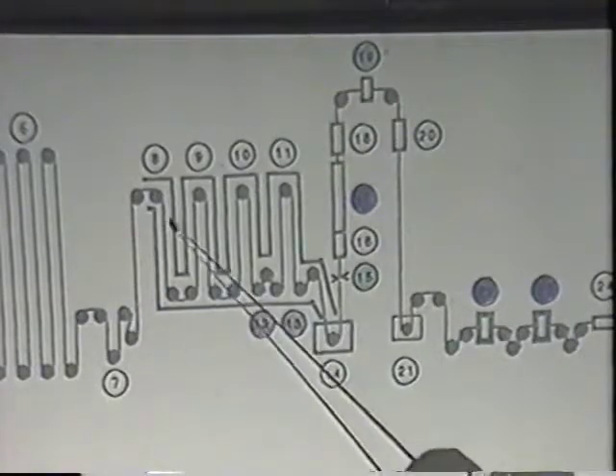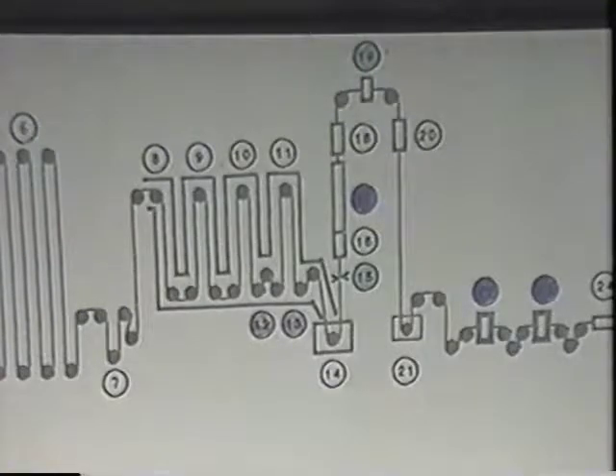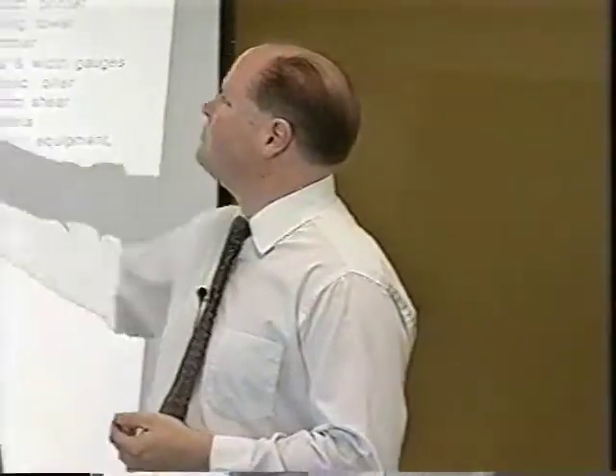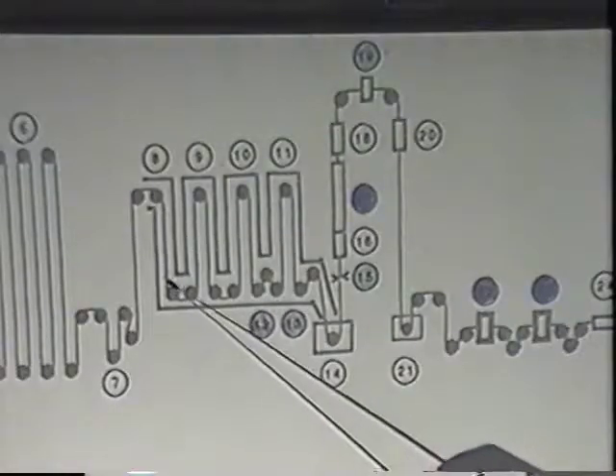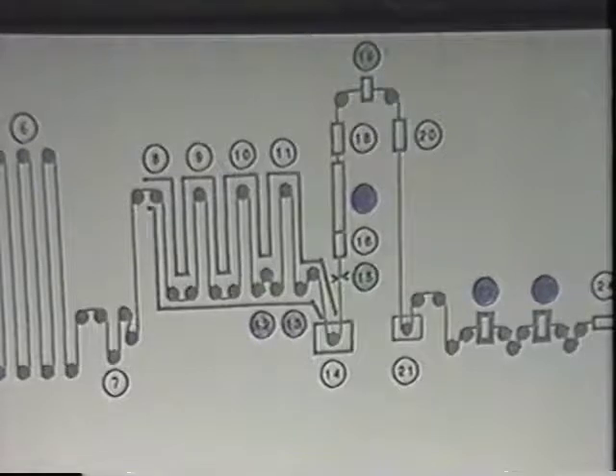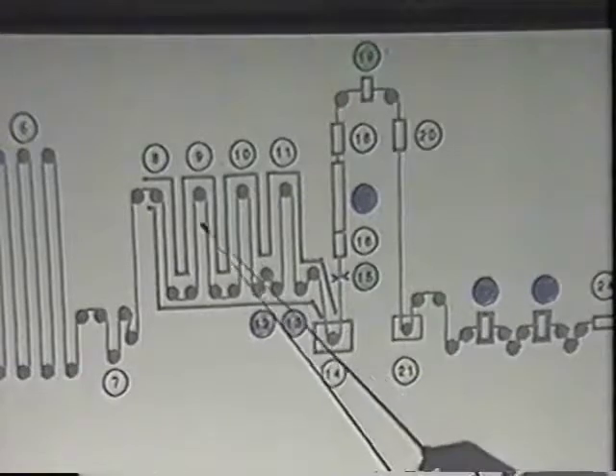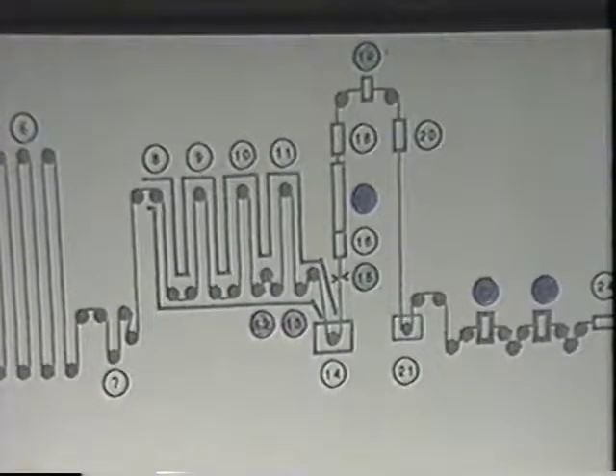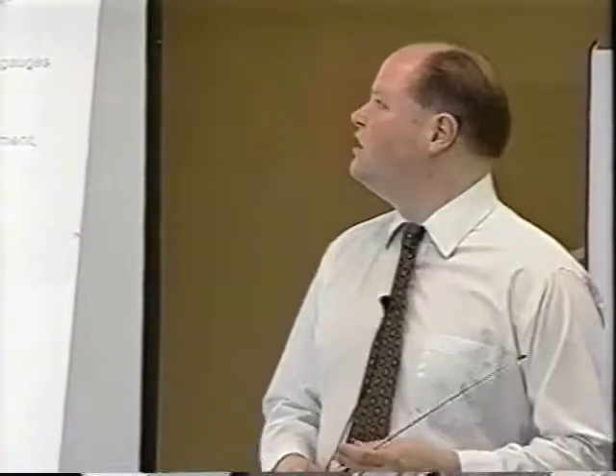So we clean it here, then it goes into our annealing furnace, kind of similar to the one that you talked about this morning on our CHTL, in that it's a reducing atmosphere, runs about 4% hydrogen, the rest is nitrogen. It goes into the preheat section, which will heat it up to about 350 degrees, just to get things going and loosened up, keep the tension straight. Then it goes into a heat section, where it heats up to the temperature desired to get the properties that we want. That could be anywhere from about 1300 degrees to about 1550 degrees, depending on the steel grade and what we want out of it when we're finally done.